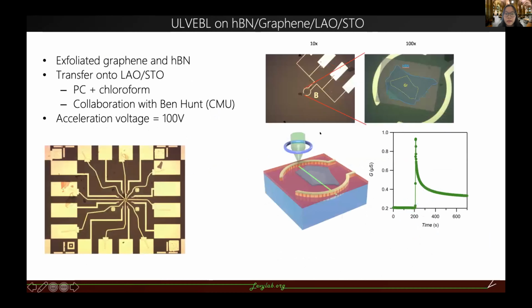And more recently, with the help from Ben Hunt from CMU, we have exfoliated a graphene and boron nitride stack, which will provide better graphene quality. And we transferred it onto the LAO/STO structure, and also we're exposing these nanowires, and we can observe a conductance jump from this writing process. And this is an optical image from a typical sample we have.